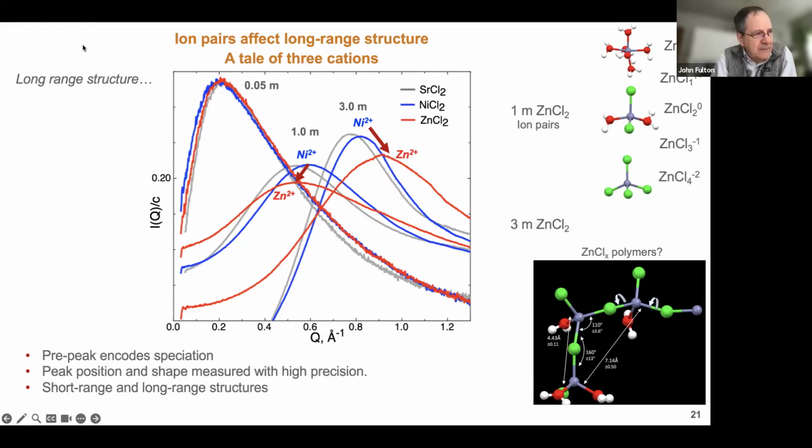But yes, we've been looking at molecular dynamics for decades, and I am not very enthusiastic about classical intermolecular potentials. Lennard-Jones potentials are not appropriate for really describing the cation-anion interaction. We've had a lot of luck with DFT-based molecular dynamics, and it's a dramatic change in the fidelity of the simulation to do high-level DFT simulations, using both normal DFT and hybrid DFT functionals.